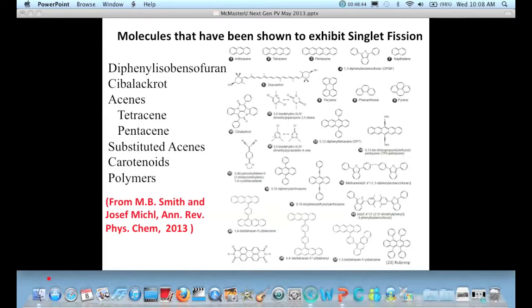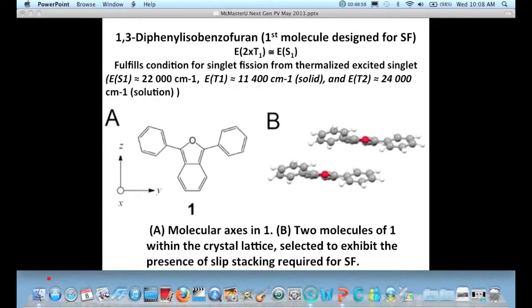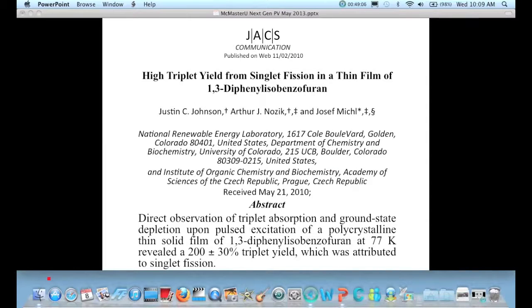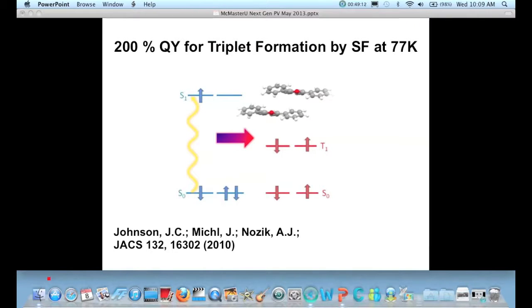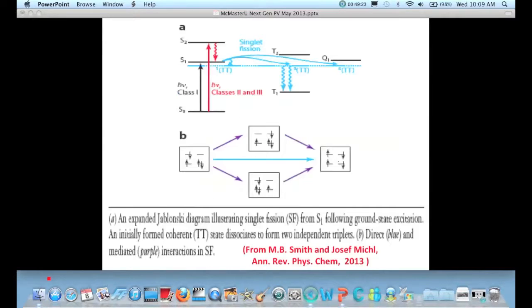So this is being studied. There are many molecules that show this, and there's a nice review coming out in Annual Reviews of Physical Chemistry by Joseph Michl and Millie Smith from CU, who we collaborate with. We studied this molecule, which has a slip stack orientation in the crystal. And in this paper, we showed it has exactly 200% quantum yield. So it gives you, right at the band gap of 2 times the HOMO-LUMO transition energy, 2 triplets, and these can be harvested in a solar cell.